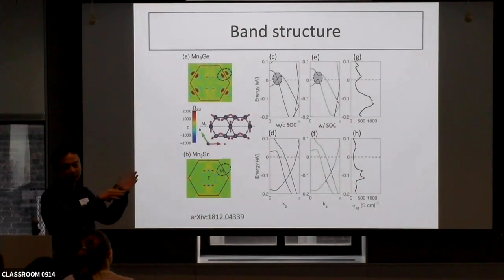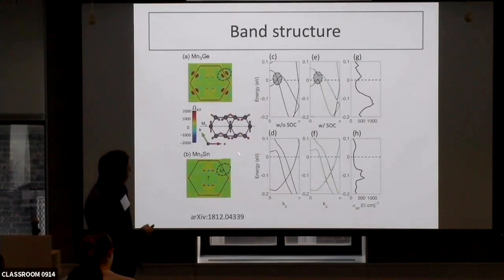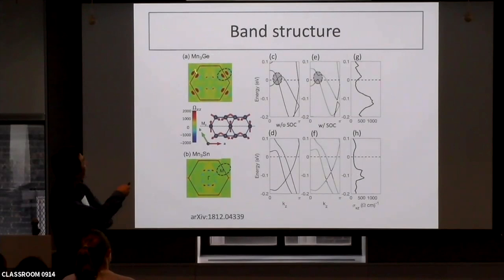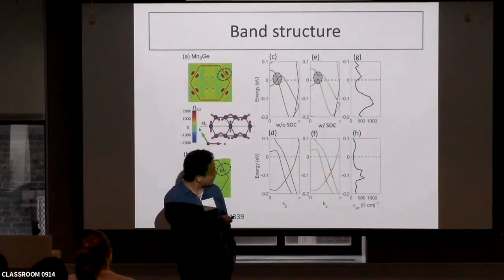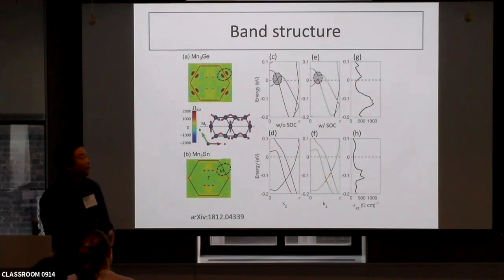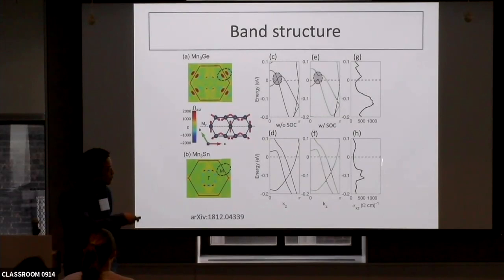Comparing the two materials in ab initio band structure: the color shows Berry curvature with different signs — blue and red are opposite sign. The energy-dependent sigma_xy is relatively flat for the Mn3Sn (T material), while for the germanium material there is a small peak. The distance between the Fermi energy and this small peak is on the order of 100 Kelvin. It is not surprising then that the germanium one easily deviates from the Lorenz number. Germanium has relatively weak spin-orbit coupling — if SOC is strong enough, it increases the anti-crossing gap, and the Berry curvature is smeared more in momentum space and energy, giving a more averaged distribution. With a weaker SOC the germanium case has a small gap with a sharp feature, providing one more possibility to violate the Wiedemann-Franz law.